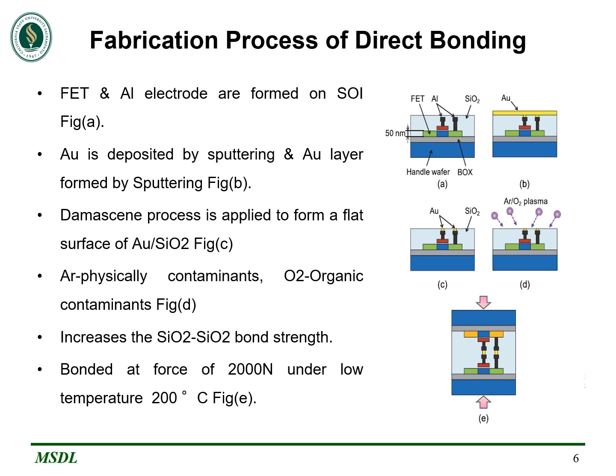The chip surface is activated by argon plasma and oxygen plasma before the bonding process. Here, argon plasma is used to physically remove the contaminants, and oxygen plasma is used to remove the organic contaminants and to create the OH group on the surface to increase the silicon dioxide bond strength, as shown in figure D.